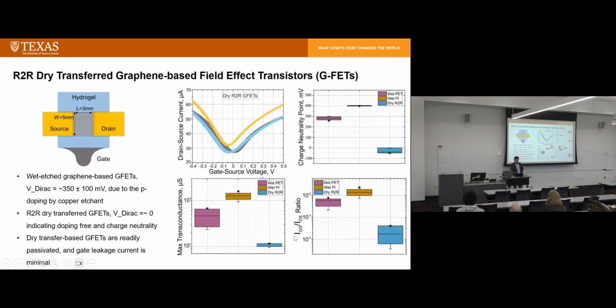Another characteristic we're looking at is the leak current between gate and source versus drain and source. You want this leak current to be as small as possible, because if you have large gate current, that's not a field effect transistor anymore. So for wet transferred PET and wet transferred PI, those are graphene on PET and PI, those samples have very high leak current, so that's not good for field effect transistors. Whereas our dry transferred samples have very low leak current. That means the quality is better for electronics applications.